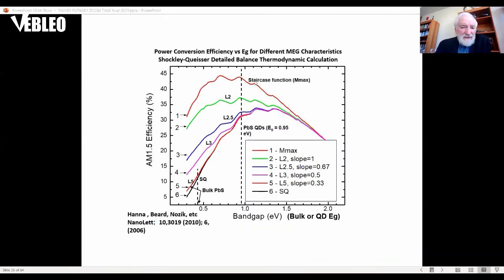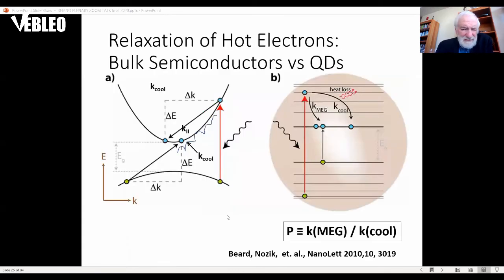And you can see that the staircase will give you a maximum efficiency of close to 45% versus the Shockley-Queisser limit, which is 32%. But if it's not perfect, if it doesn't give the staircase, but, say, has an onset at twice the gap and then a linear function, which is a linear increase of the quantum yield with increasing photon energy, that's labeled as linear 2. So it's twice the gap. So L2, L2.5 means the onset of the multiplication is this number of band gaps in the photon energy.